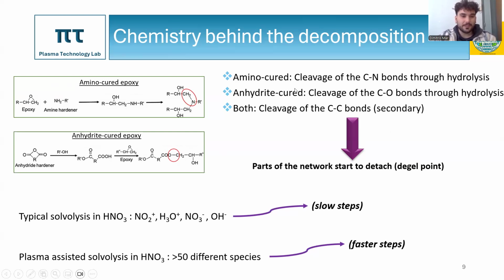Now, in typical solvolysis in nitric acid, only a few species participate in those reactions. That's why the degradation steps are very slow. But when we assist the solvolysis with plasma, over 50 different species participate in those reactions. That's why the decomposition of the matrix is much faster.